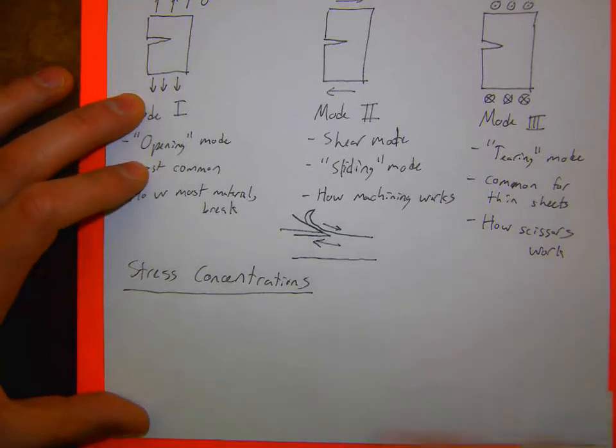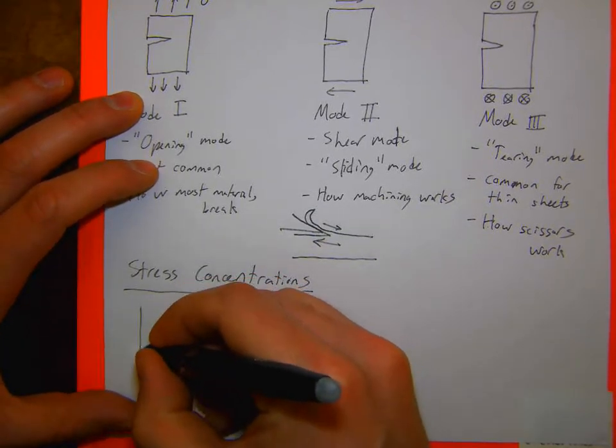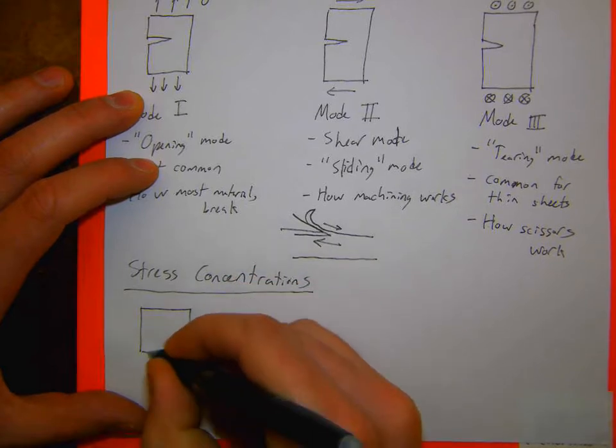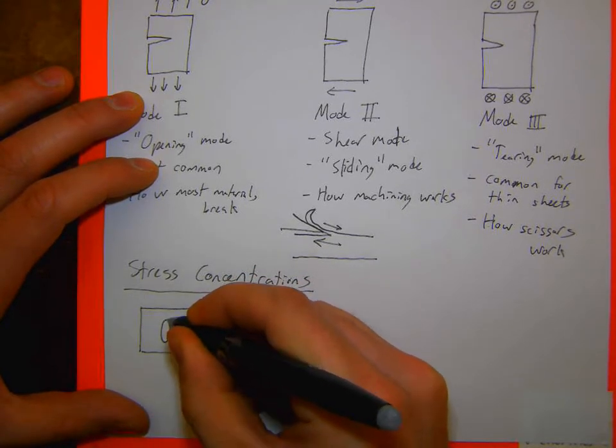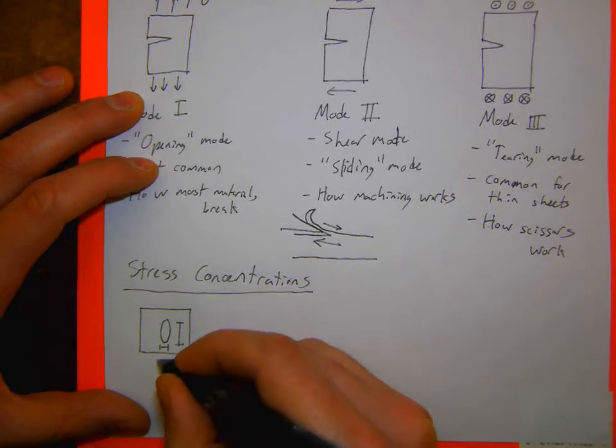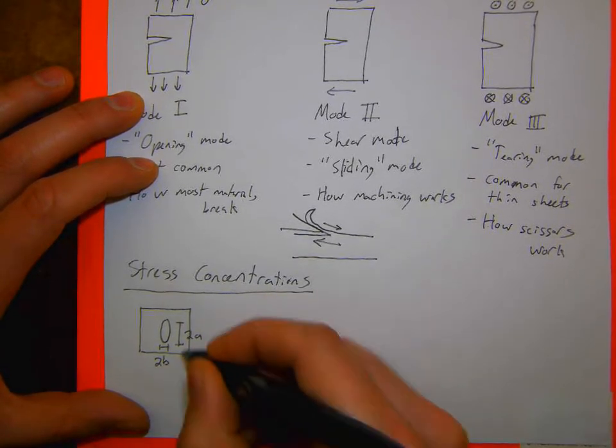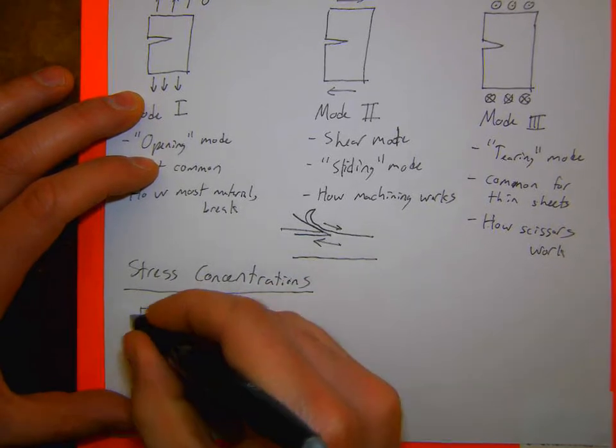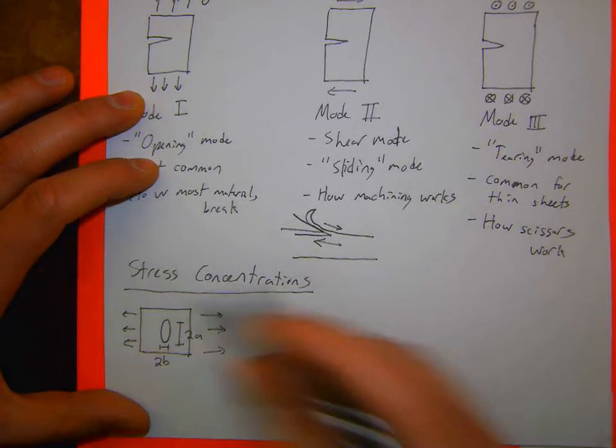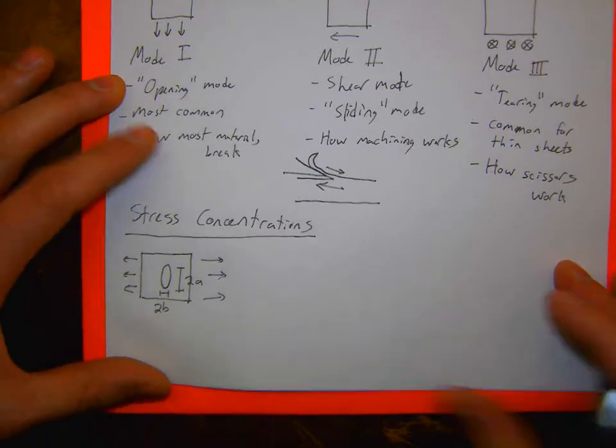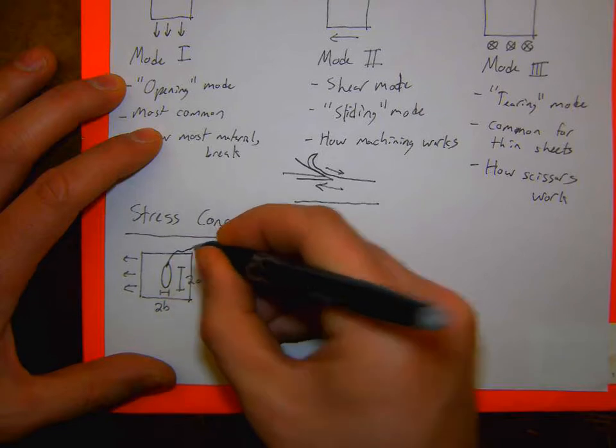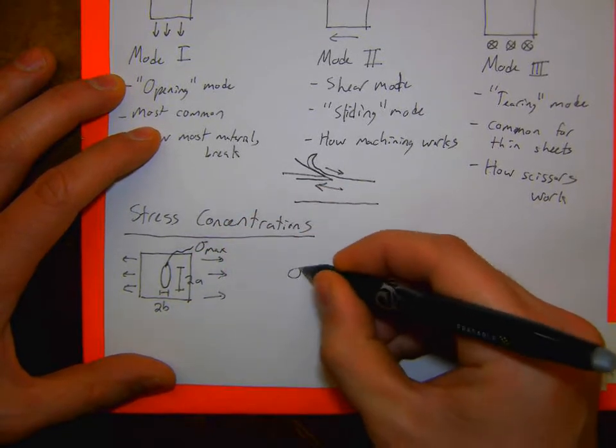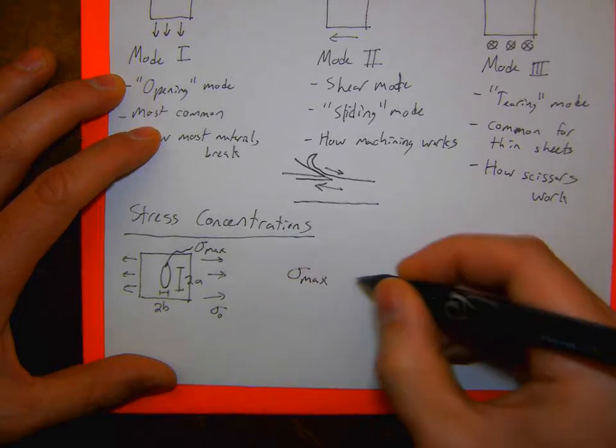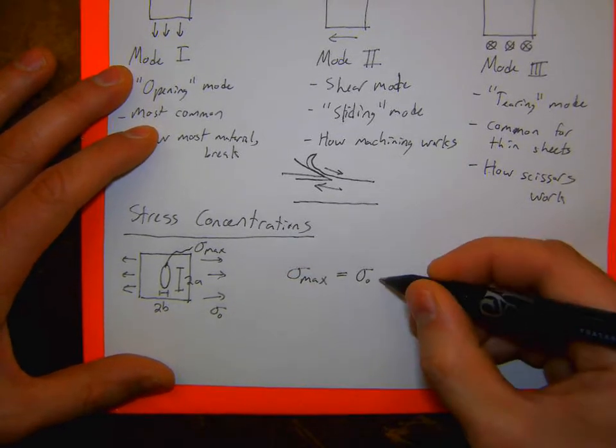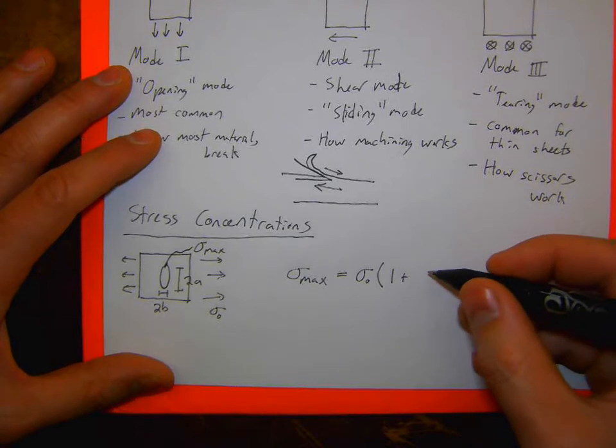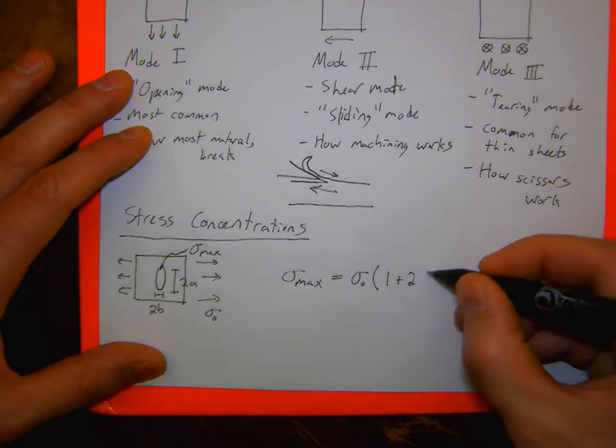Cool. So now I had drawn that plate getting pulled with some elliptical crack in it with height 2A and width 2B. And there's some far field applied stress on this. And I had given you the relationship before that the max stress here at the top, sigma max, is equal to the far field applied stress, sigma naught, times 1 plus 2A over B.